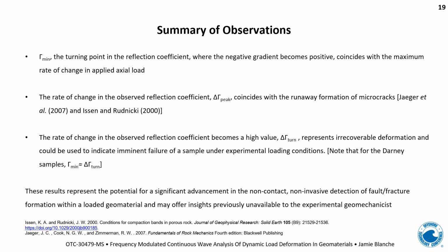So, and certainly for the Darney samples, that minimum in reflection coefficient seems to correlate with that turning point. So overall, these results represent the potential for a significant advancement in non-contact, non-invasive detection of faults and fracture formation within a loaded geomaterial or concrete, and may offer insights into previously unavailable data to the experimental geomechanicist.